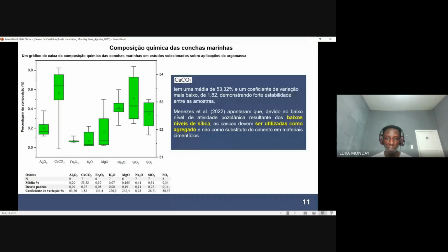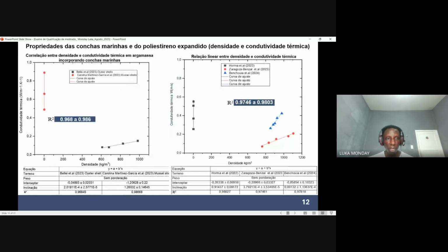However, other authors also explored using these materials based on the content of seashell, and using this material as a cement replacement is not advisable. However, using this material as a substitute for aggregate is the best option. Used as a cement, it has a low pozzolanic reaction and the level of silicate is very low with respect to this material. So it is advised to use these materials as an aggregate instead of as cement replacement based on the analysis as shown here.